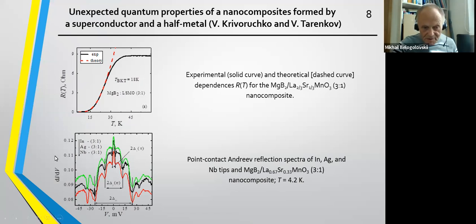Even more exotic were the results of point contact spectroscopy on such a nanocomposite, where two superconducting gaps characteristic of magnesium diboride were revealed. So that is natural, but there was also a third gap above them, higher than them. And this third gap was observed very regularly and repeatedly. So there are no doubts that something like a third gap exists only in this nanocomposite. The explanation of the authors is that it is a gap induced in magnetic manganite by proximity with a strong superconductor like magnesium diboride.